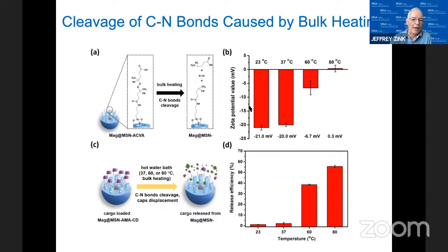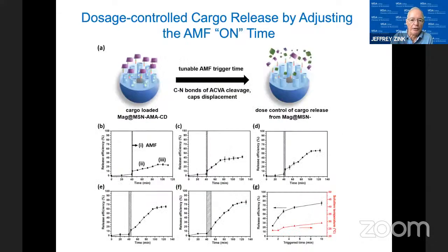So we can, of course, show that just by heating it in the water bath, and we can demonstrate that there is drug release. So that works very nicely in a hot water bath. We could demonstrate that with a probe sonicator, not any HIFU, but just ordinary sonication, and that shows that that could work. And then we were able to show that with high-intensity focused ultrasound, excuse me, I'm on the wrong subject here. This also works with ultrasound.